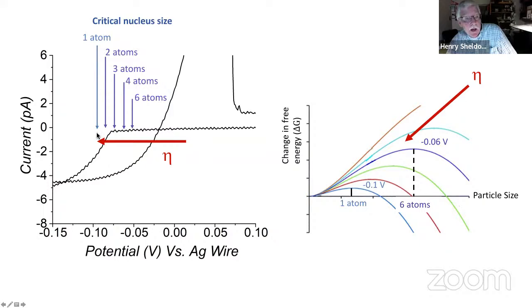When you're at 1 atom, this is right at the limit of what we can measure because nucleation is so fast. Once you get to this potential range, people consider the nucleation to be instantaneous because it comes so fast. You can't see the nucleation kinetics. All you can see under those conditions is the growth of the particle limited by diffusion. Anyway, this is a really cool experiment.